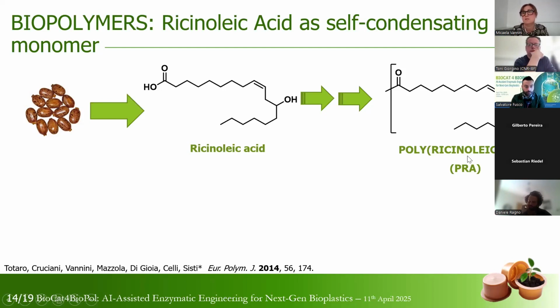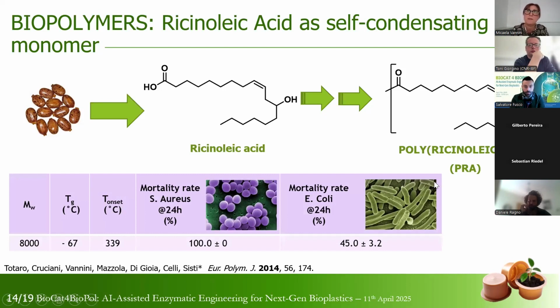A few years ago, we obtained PRA, poly(ricinoleic acid), and we observed that PRA is characterized by intense antimicrobial properties. In particular, we recorded a mortality rate against Staphylococcus aureus after 1 day equal to 100%, total antibacterial activity. The mortality rate was lower against Escherichia coli, and reaches in any case 45%.